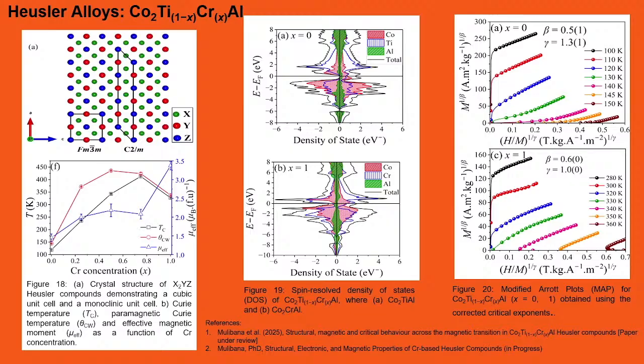The minute you start adding chrome into this lattice, things start misbehaving. The titanium and the aluminium start to randomize. And this has quite a big impact, of course, here in the density of states. Also, again, there is a transition temperature to show.